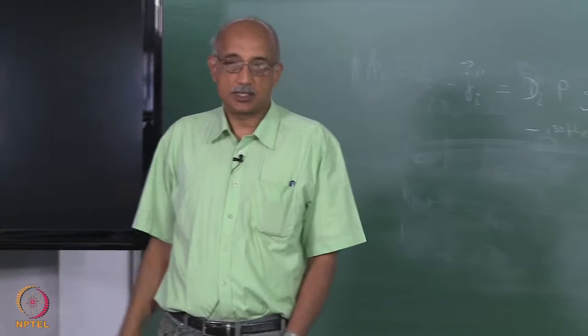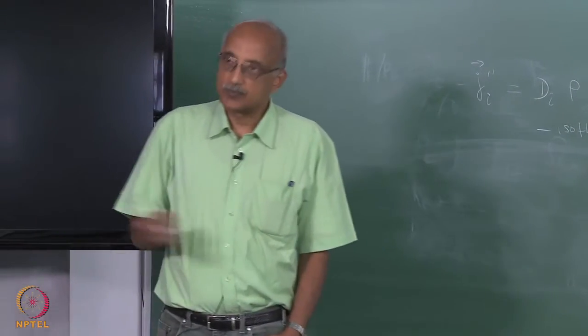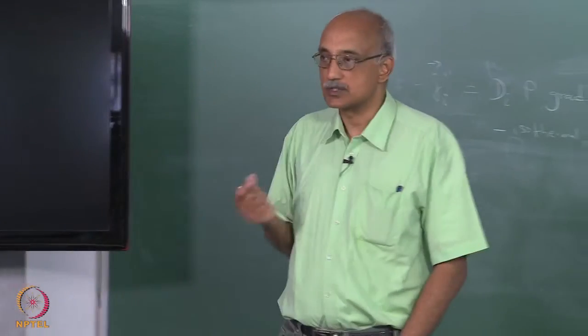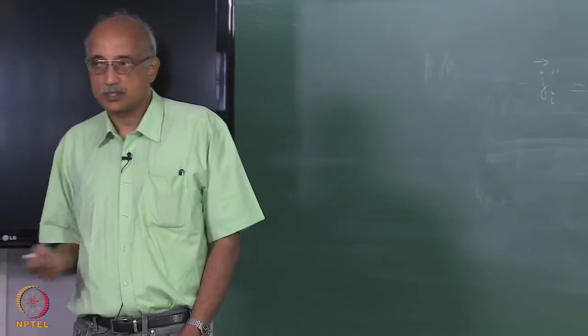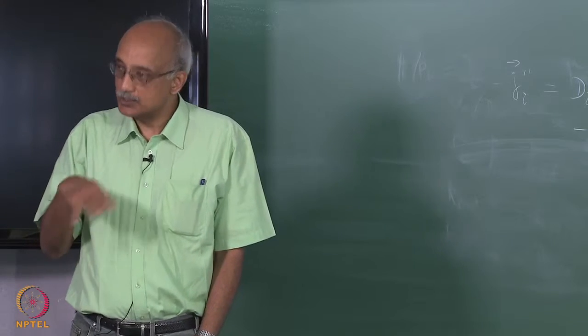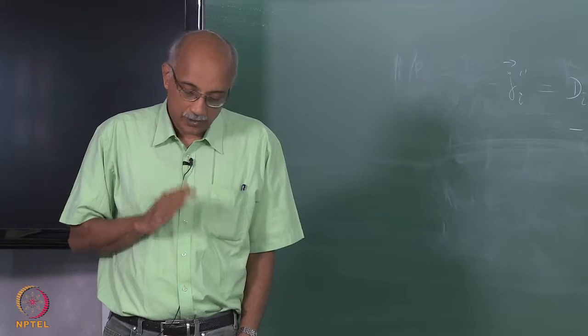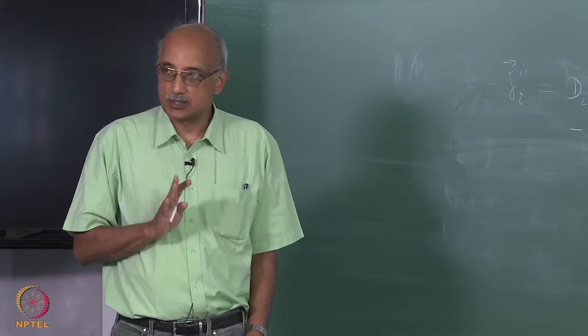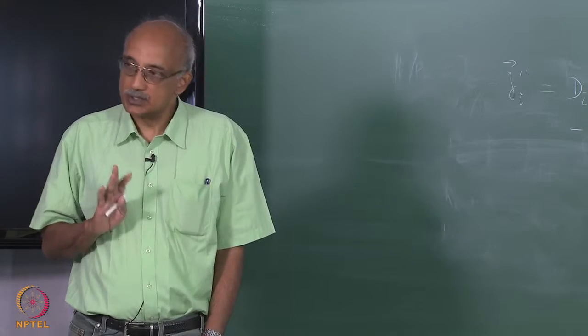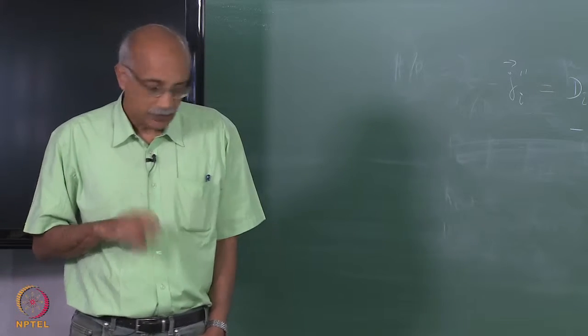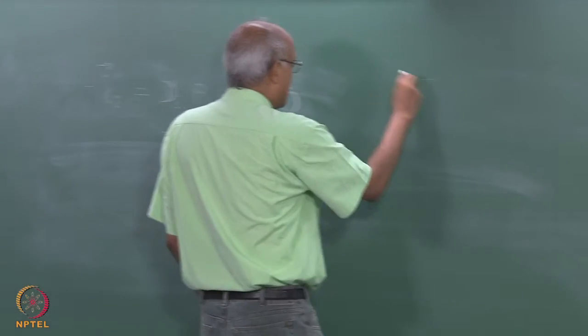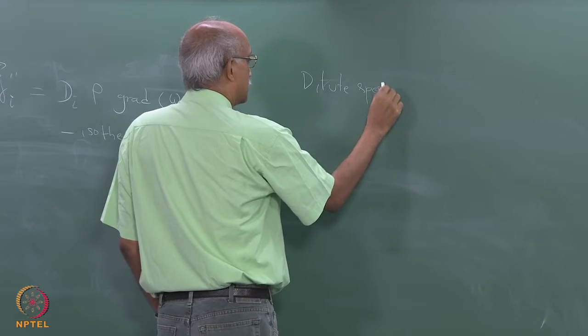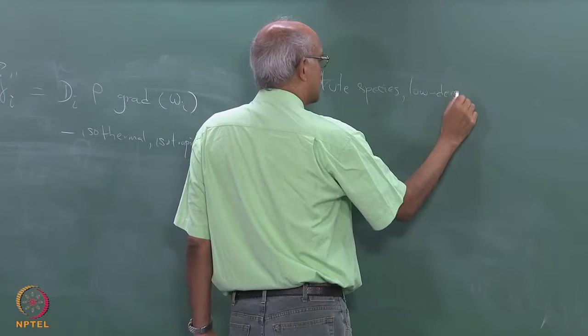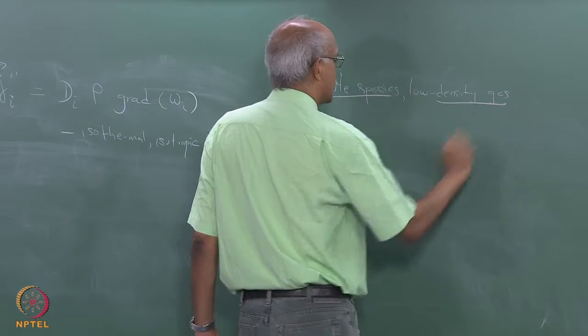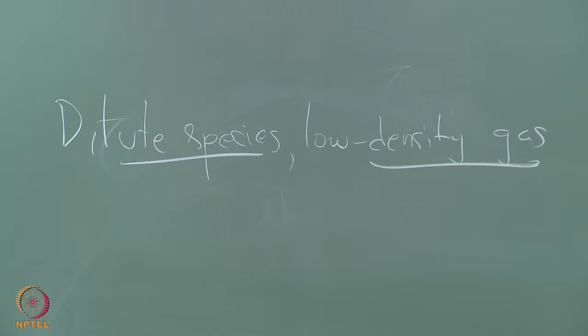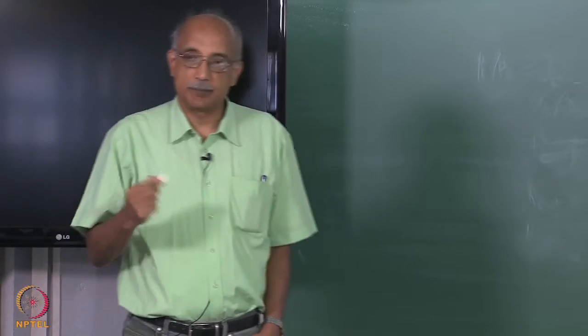of species. But in a real system, particularly in a CVD reactor, you know that there are going to be hundreds of species. So, the effective diffusion coefficient of a single species is going to be dependent not only on the prevailing temperature and pressure conditions, but also the mole fractions of all the species comprising the system. Because when you have a case where you have a dilute species which is diffusing in a low density gas, which is typically the case in a normal CVD reactor. So, for that particular combination of a dilute diffusing species in a low density gas, you can write the effective or prevailing diffusion coefficient as the aggregate of all the binary diffusion coefficients.